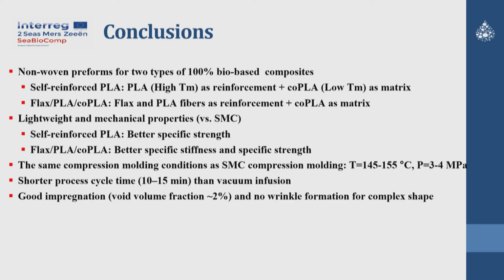Due to the proximity between the reinforcement and the matrix, because we implement the matrix and reinforcement in the same filament, the impregnation path was relatively short, and we could obtain excellent impregnation quality. The void volume fraction was lower than 2%, which is almost aeronautic part grade. And in terms of drapability, we obtained no wrinkle formation.